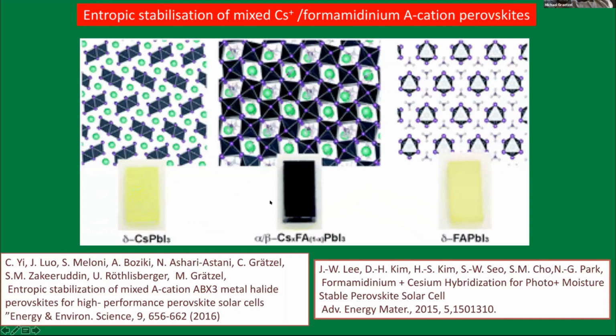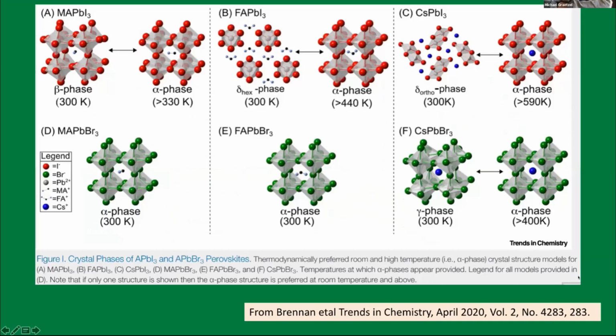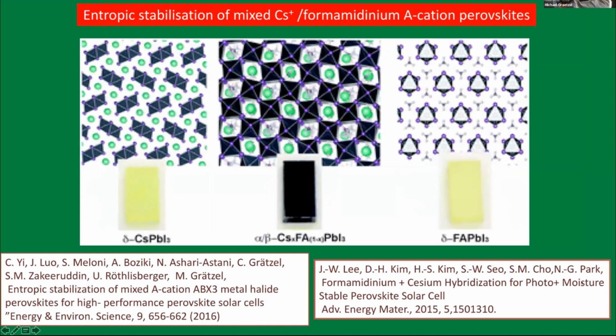And so then the same thing happens when you add cesium to the formamidinium. And it's very striking because the cesium itself doesn't form a stable perovskite at room temperature. So it looks yellow. That's the yellow cesium lead iodide film. Formamidinium doesn't either, but just mixing those, you can grind them together, they turn black. Okay, and you see also Namgyu Park here, and he was one of the first ones to do that experiment, and we did some theory. We published about the same time, and we tried to understand why this was going on.